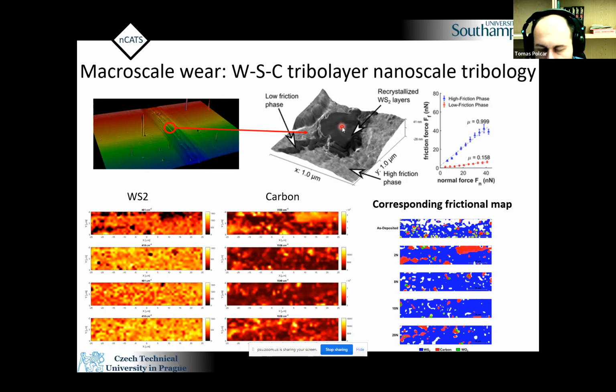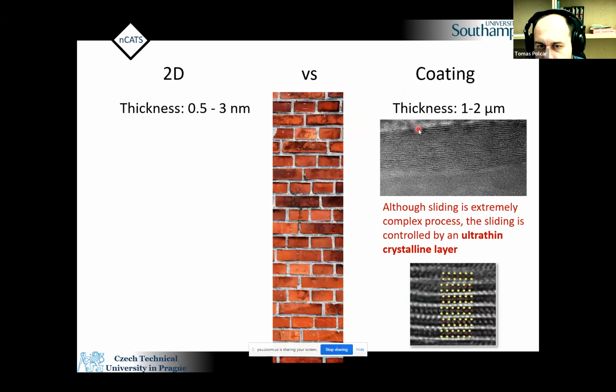So we can conclude here that if I slide macroscopically these very complex coatings containing, for example, tungsten and sulfur, I will end up with almost ideal 2D material, and it looks like this. So this is the surface, and if I really do detail of some of these parts, this is what I will get. You see, this is almost ideal material. There are almost no defects, in fact, or very few. So this very stochastic random nature of sliding results in production of an ultra-thin crystalline layer, which is a low friction material.